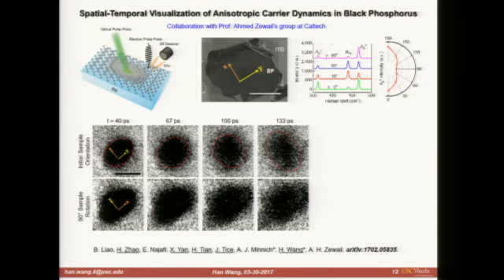And then we turn the sample by 90 degrees, so now the X direction is along here, and Y direction is along here. We shine the pump laser and let the carrier diffuse. You can see now the carrier moves much faster along this direction, which is still the X. So the spot elongates faster along the X direction and much less so along the Y direction of the crystal.